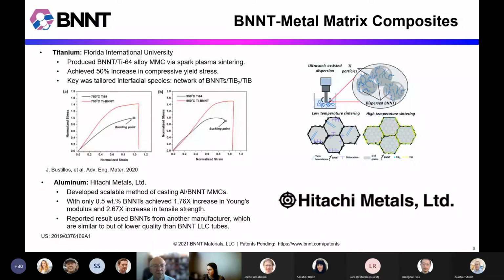So starting out with metals here, to talk a little bit about some work that's been done with material that our company produced, is some work with titanium MMCs out of Florida International University by Arvind Agarwal. He used a unique method to actually disperse the boron nitride nanotubes in titanium. He used an ultrasonic assisted dispersion method to get the boron nitride nanotubes coating the interface of those grains.